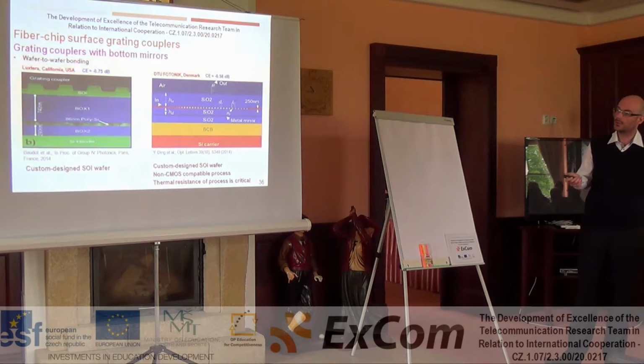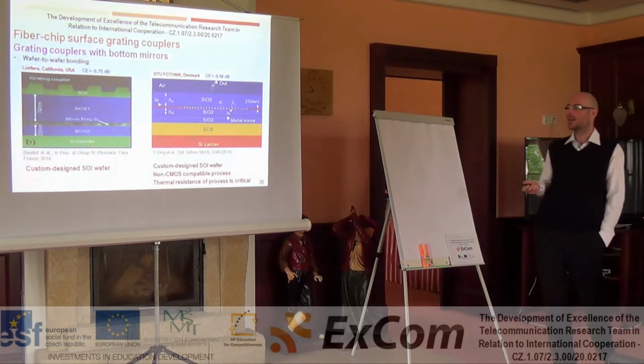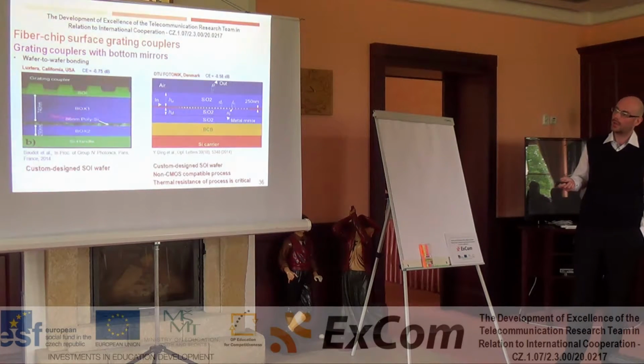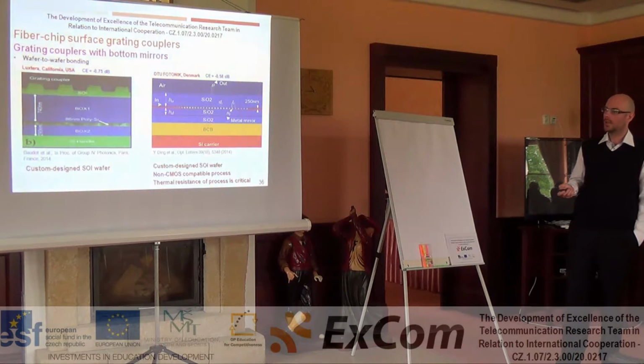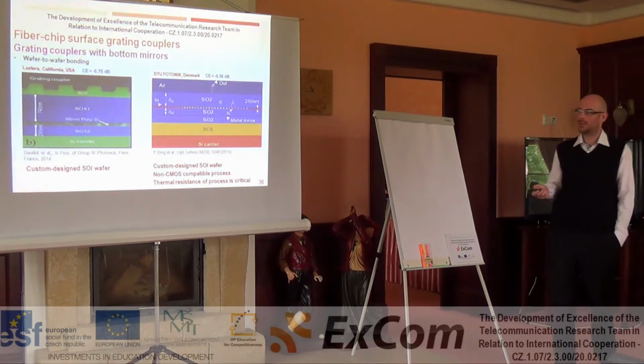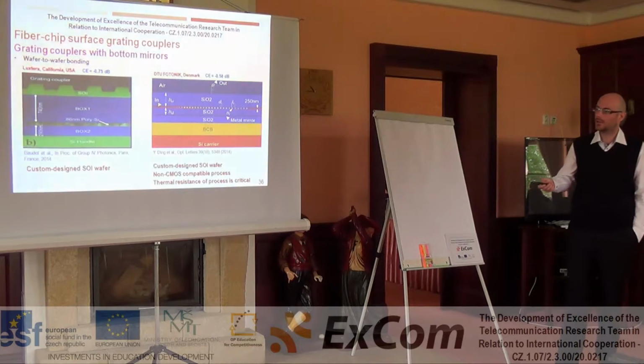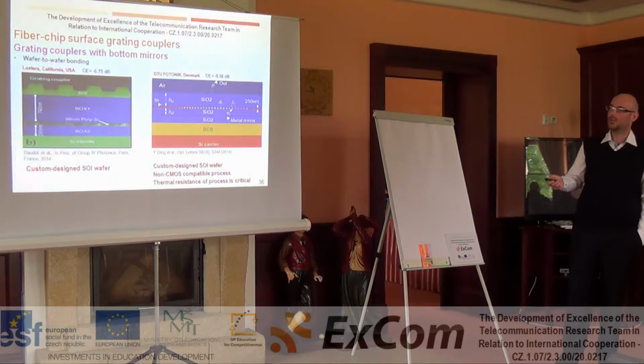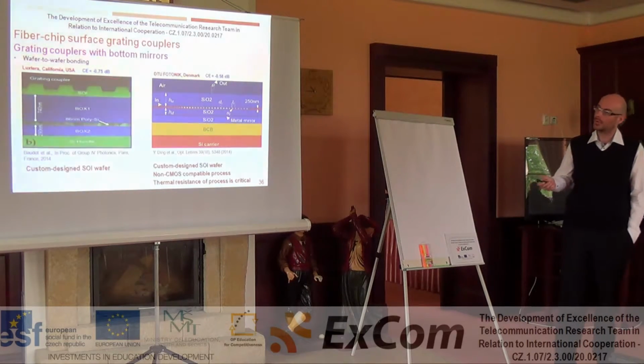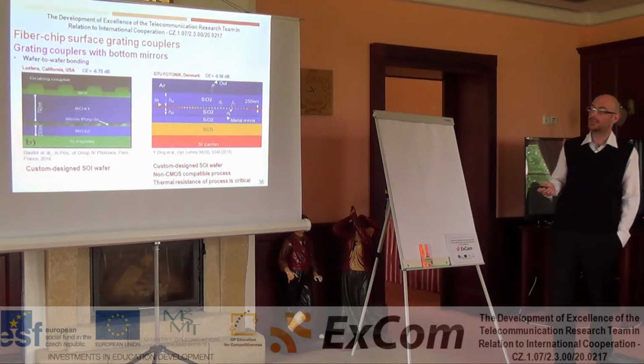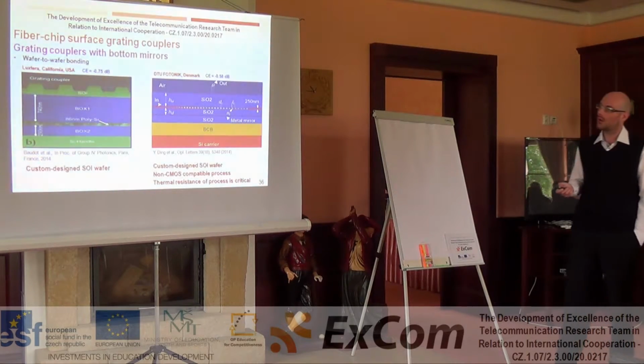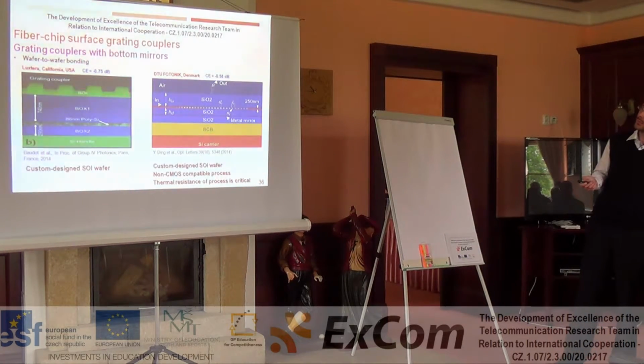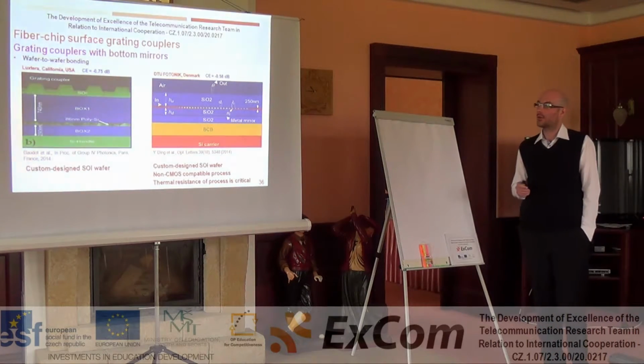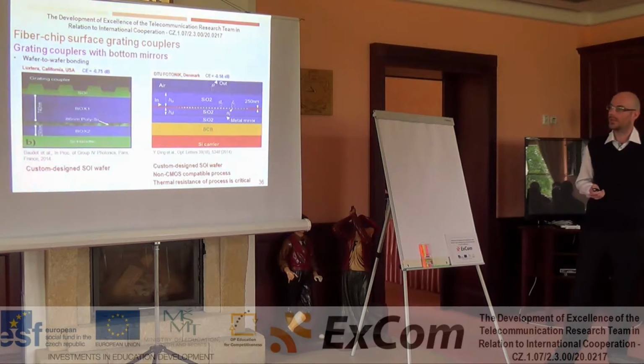In this configuration we talk about a double SOI structure because we have here two box layers. Here you can see this layer and this layer create a mirror. Thus the power that is radiated toward the substrate is constructively diffracted towards the grating and then towards the fiber. Luxtera has achieved very nice coupling efficiency below 1 dB. To be more specific, they achieved minus 0.75 dB coupling efficiency.